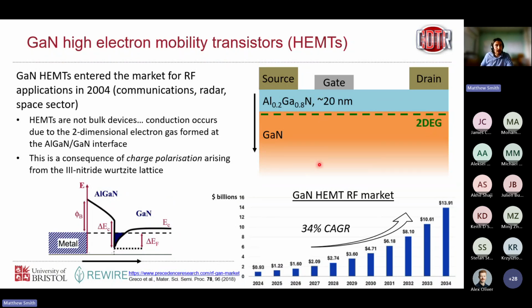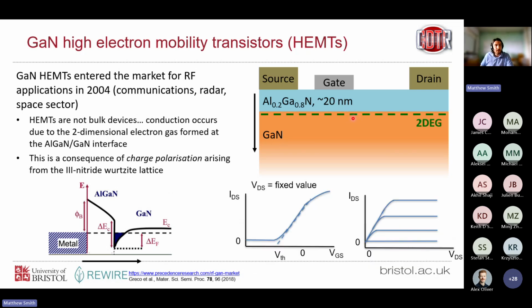So it's still a very growing market, but these devices are really focused on the RF market, so switching at kind of gigahertz levels, still at high power, but not really focused on power devices. The reason for that is essentially because they're normally on. So we have this 2-DEG that exists, and we have to apply a gate bias to turn that 2-DEG off. So what that means is our threshold voltage, so the gate voltage at which the device turns off, is less than 0. So if our gate fails, if our gate driver circuit was to fail, then the device would be on, and that's not good from a power device perspective because you leave your load, your system at risk of power surges there.